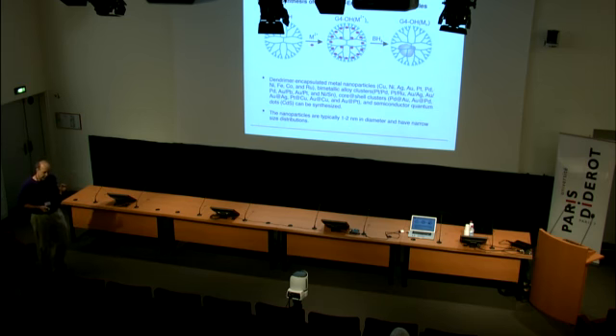We've used EXAFS and other techniques, and electrochemical techniques particularly, and the surface of this metallic particle is clean, within our ability to measure it. That means that the dendrimer itself, these functional groups inside the dendrimer, are not poisoning the surface of the particle. So this is like a ship in a bottle type of synthesis. You put the little parts in, and then you make a big part, and now it's sterically confined in there. But the surface isn't poisoned.